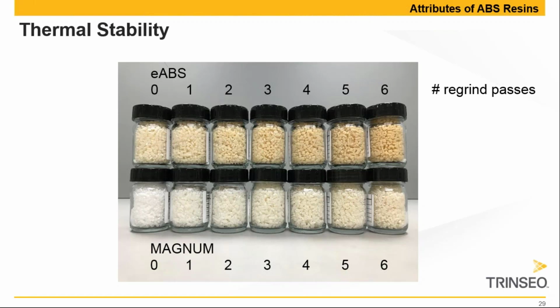And if you compare pass 6 of Magnum with pass 0, so with the start color of emulsion ABS, you could roughly say 6 passes of Magnum gives you the starting color of the emulsion ABS. Hence, the Magnum is more suitable for higher regrind loadings compared to emulsion ABS. That will require more color corrections and of course then more cost for pigment.